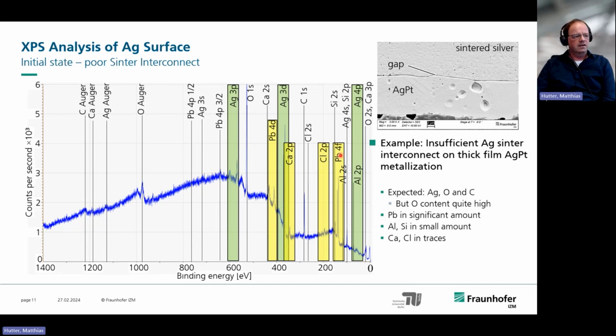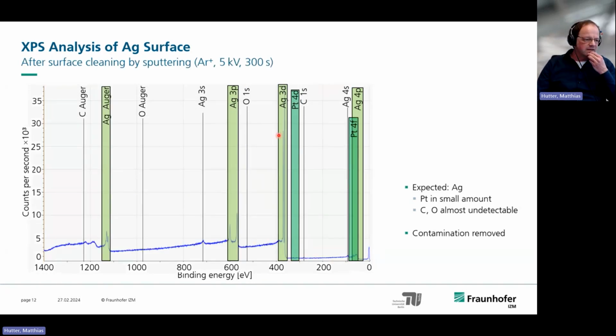And if we then do back sputtering using argon ions, which is also done in the XPS analysis tool, at 5 kilovolts for 300 seconds, where we don't exactly know how much we back sputter, but let's assume 20 nanometer, 50 nanometer, we see that these contaminations are gone. So we know this was more or less a contamination on the surface of the silver platinum thick film metallization.